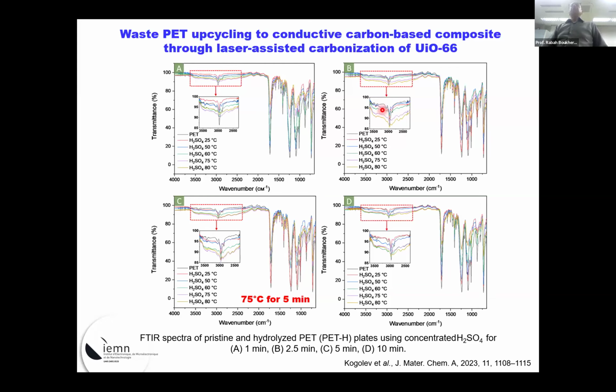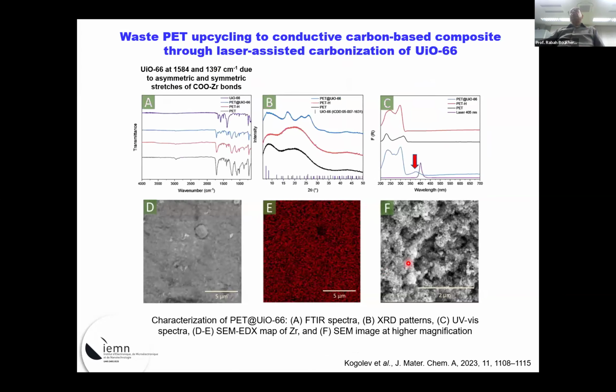So coming back to our plastics, what we did, we optimized the conditions of the hydrolysis, and we found the optimized conditions. It's sulfuric acid at 75 degrees C for 5 minutes. If we do that, then we add this zirconium salt, then we form this very nice zirconium MOF on top of the plastic, okay? I'm not gonna go too much in detail, but what's important, now that you see there's a small absorption of this MOF on plastic, and the reason why this is important is because we use an LED at 405 nanometers. So the ideal would be to have it here, it will be the optimum. But if we have it close enough, then we can transform this MOF layer to graphene and zirconium carbide.